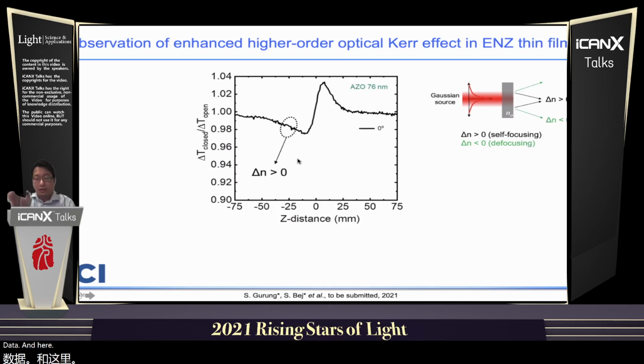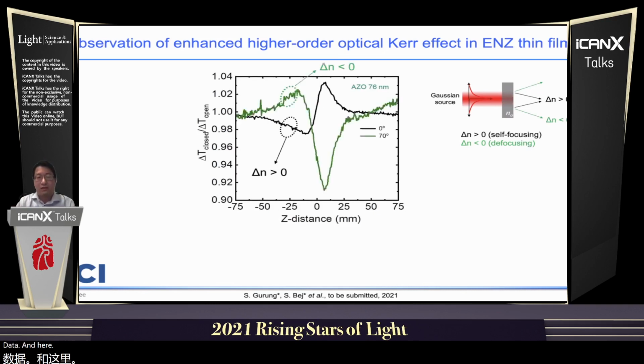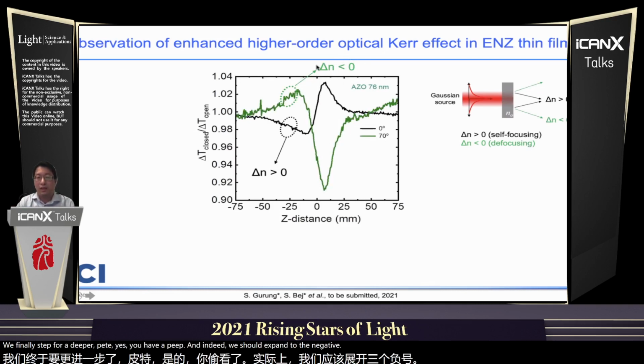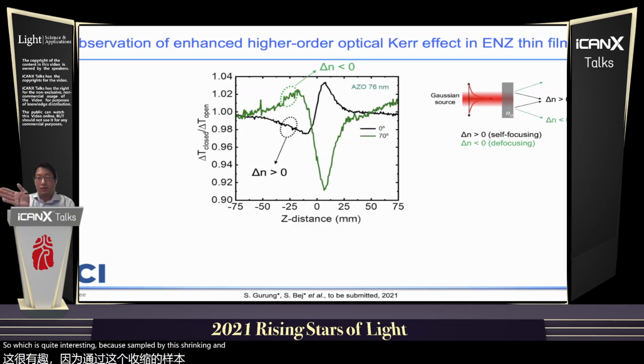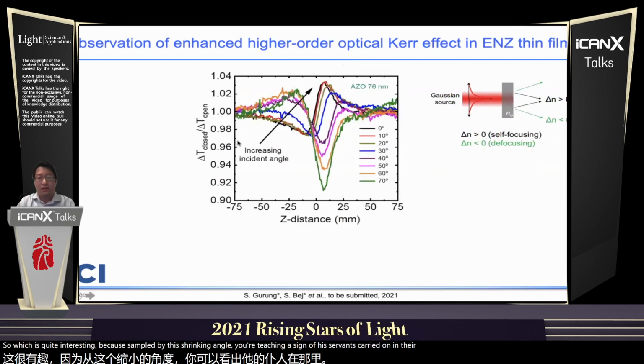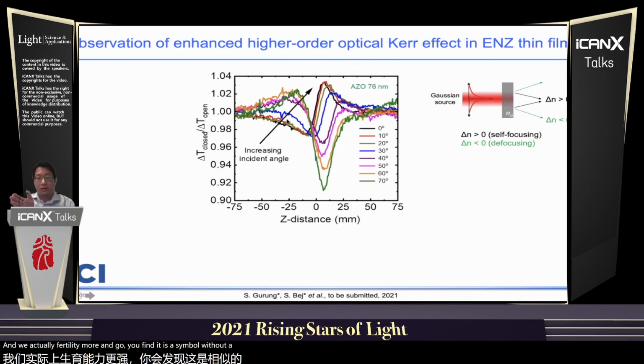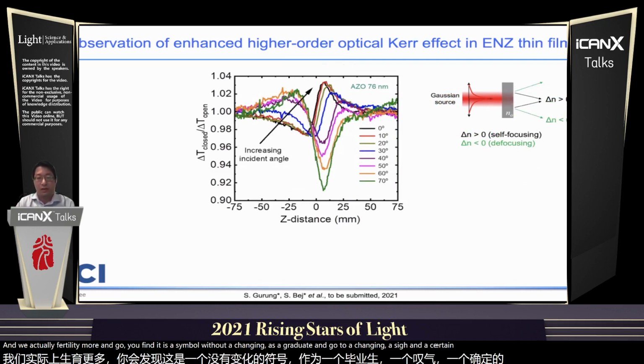But when we change the angle of the excitation, if we go to 70 degrees, we find that instead of a dip to a peak, you actually have a peak and then a dip, which corresponds to a negative delta N here. Which is quite interesting, because by just changing the angle, you're changing the sign of this nonlinear phase change. If we go to further angles, you find a similar result: by changing the angle gradually, you change the sign, and at a certain angle you have a higher amplitude here.